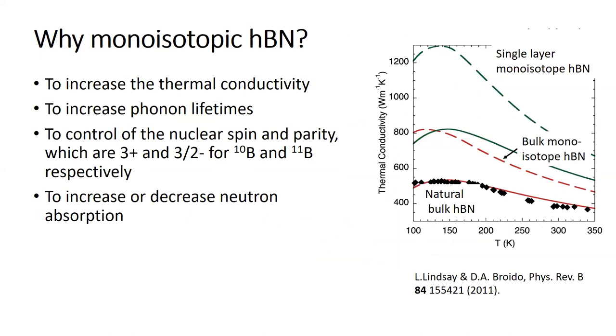So again, just to emphasize, there are several reasons to be interested in using just one isotope or another. You can certainly increase the thermal conductivity. Natural boron nitride has a thermal conductivity shown here, and it is predicted for both monoisotopic forms to increase from about 400 to 800, and if you go to single layers, you can get even greater enhancements. So changing the thermal conductivity is one aspect. Changing the phonon lifetimes is another; we'll talk more about that. They have different nuclear spins, so that could potentially be of interest. And as I've discussed, increasing or decreasing neutron absorption is a possibility.